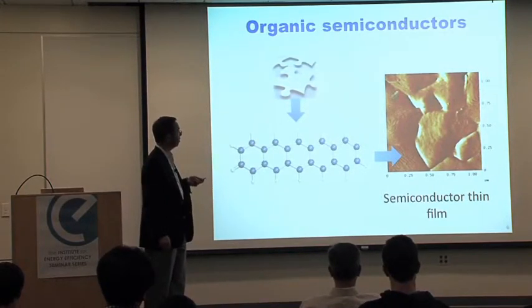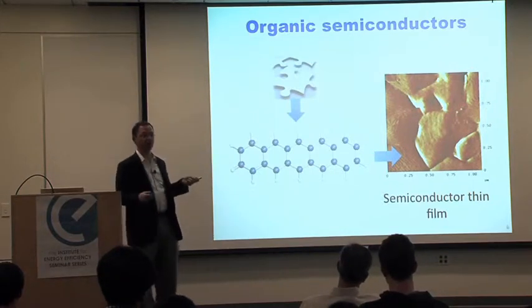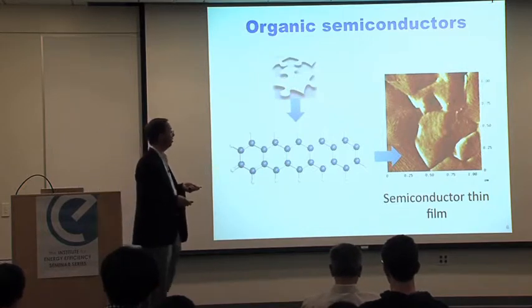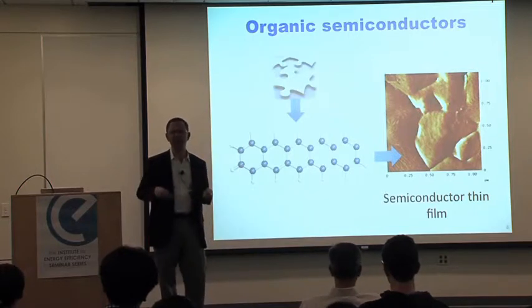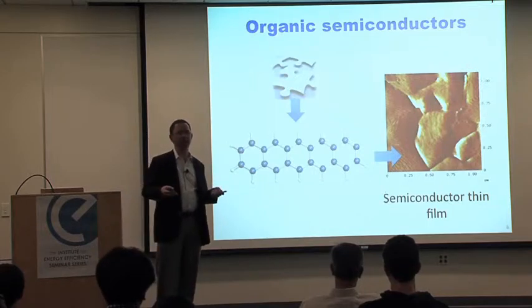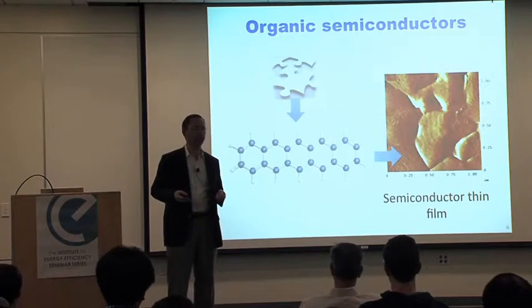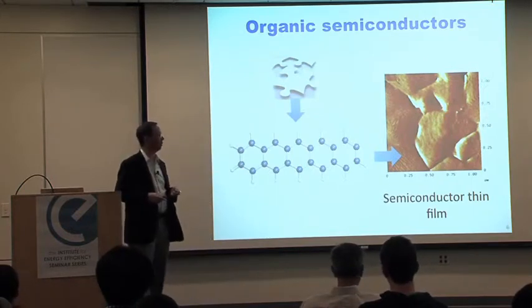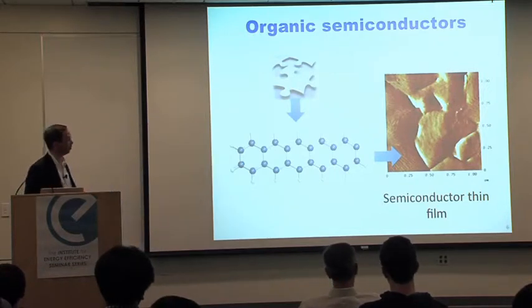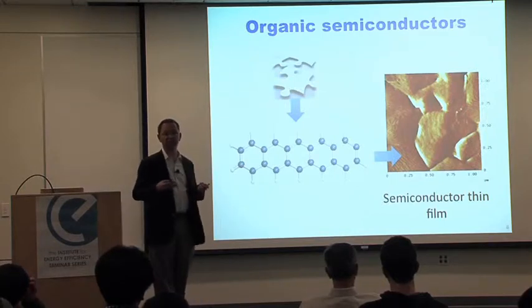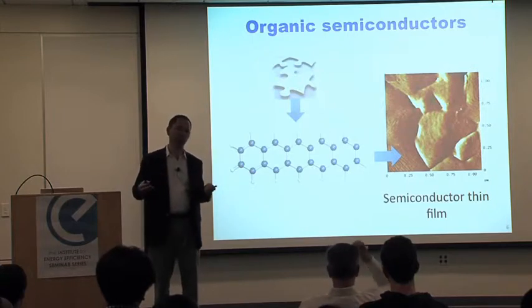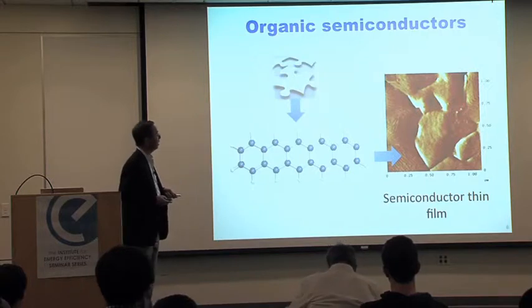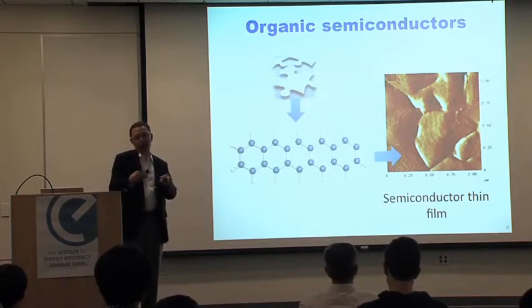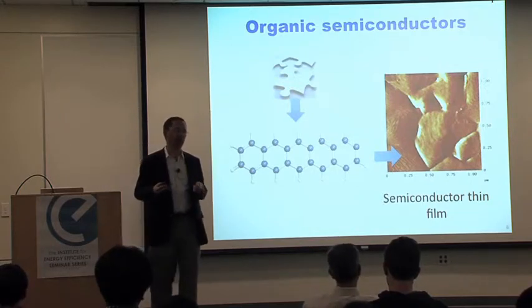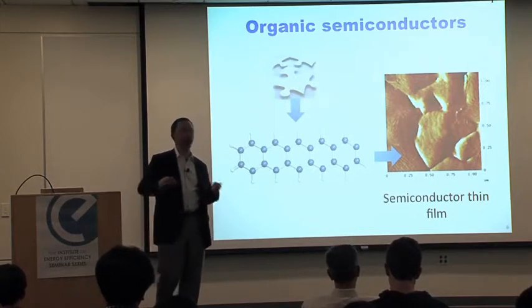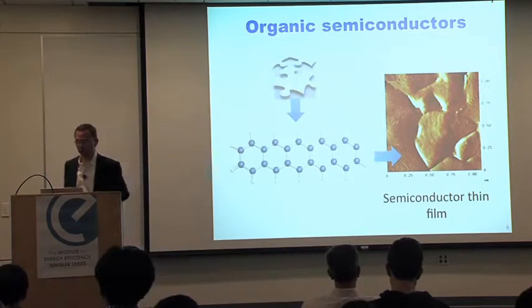And that you can make films using very simple either vacuum-based techniques or wet processing techniques using standard printing or coating, and you get films which contain large densities of impurities and defects, and you have a lot of disorder, but yet you still have mobility values which are comparable to amorphous silicon or even better, and for a lot of the devices that I will be talking about are good enough. And so the fact that these materials have electronic properties which are very tolerant to defects and imperfections also allows you to fabricate these films at low temperature. So room temperature is okay, and that of course is important in terms of manufacturing, because we're talking about energy and energy savings. We also like to develop technologies where the manufacturing itself is done at much lower energy, where you don't have to heat up materials to 1,000 degrees Celsius and so on in order to grow semiconductor layers.